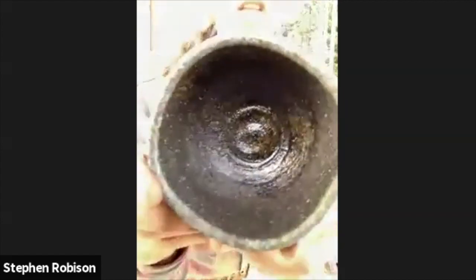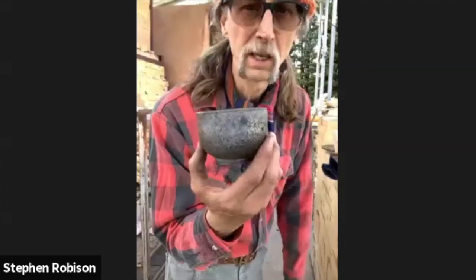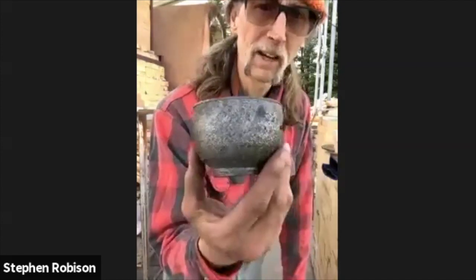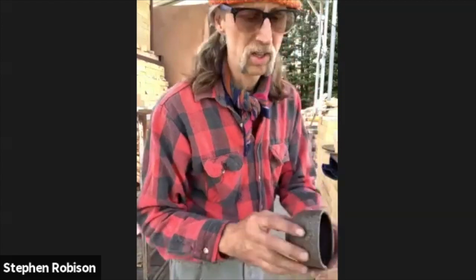So you see the glaze on the inside? Yeah. That's all wood ash. This went to cone 14, 15 probably. That clay is 100% Lake Chelan clay that you gave me. Sweet. That's beautiful, man. I'll send you actual pictures of it so you can see the surface. It got all iridescent here. I'm doing a little video on it so you'll see that. I took it out and put it in a charcoal grill over here with tons of sawdust, kind of raku'd it in a way.